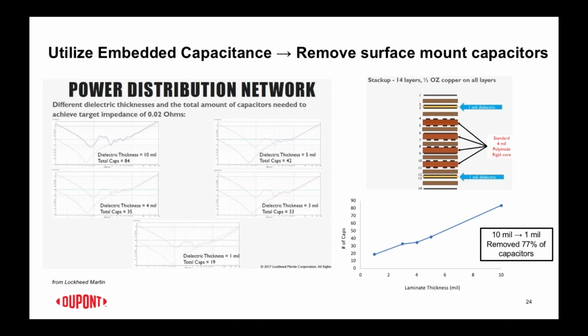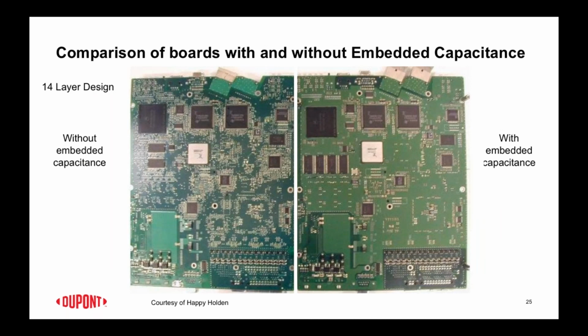And if you added up the total capacitance of those capacitors, what you'd realize is that you're only replacing maybe 1 to 5% of the total capacitance with that power ground plane, which we're calling an embedded capacitor. So again, it's really not about adding capacitance, it's about lowering the overall inductance of the power distribution network. And what are the benefits of removing all those decoupling caps? Well, you can see it clearly here. This is a picture, courtesy of Happy Holden, where you have the same board design with and without the embedded capacitance, and you can see that you greatly increase the amount of surface area available.